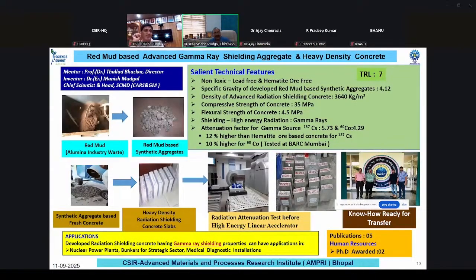Now I'll tell you the high-end application of geopolymeric concrete. We have developed red mud based synthetic aggregate. Red mud is aluminum industry waste. We developed red mud based synthetic aggregate of specific gravity 4.12. It's a high density aggregate, and using these aggregates we developed a geopolymeric heavy density concrete, which has been tested for X-ray and gamma ray attenuation at BARC Mumbai, and we got very good results of around 10 to 12% higher attenuation than hematite ore based cement concrete. So this is a unique feature of this concrete.